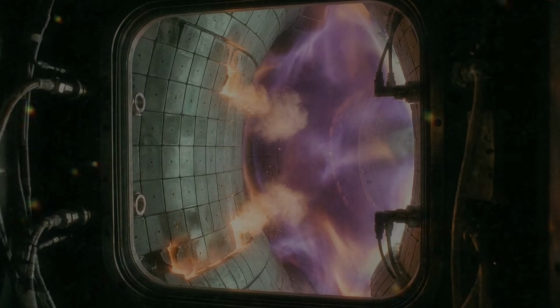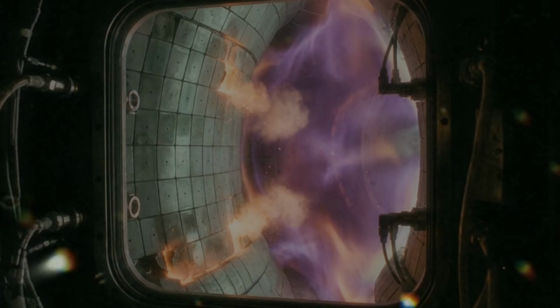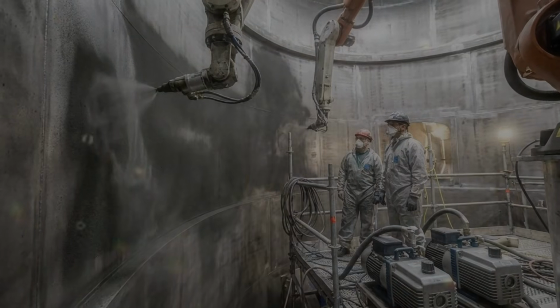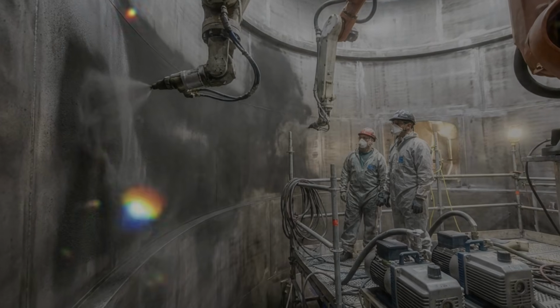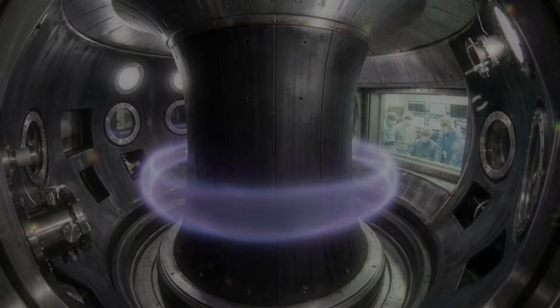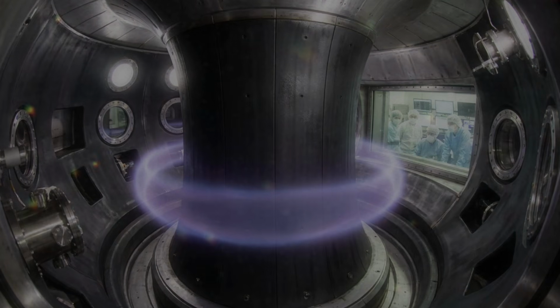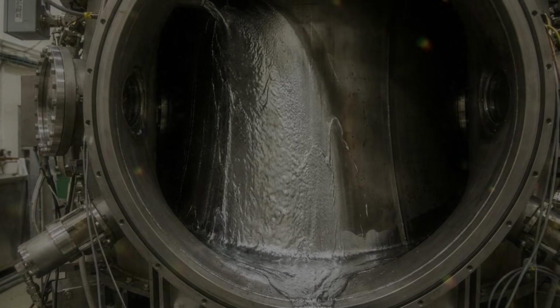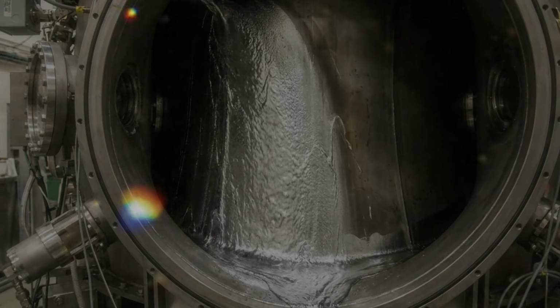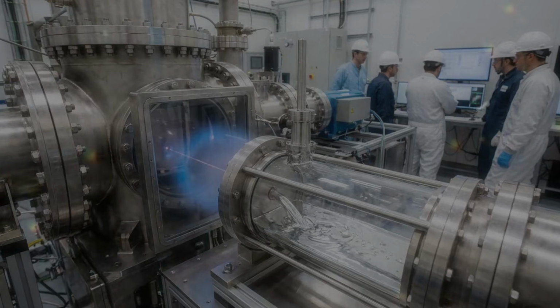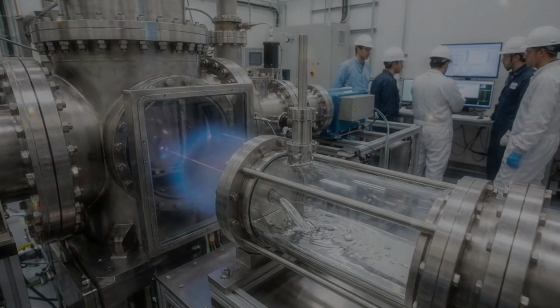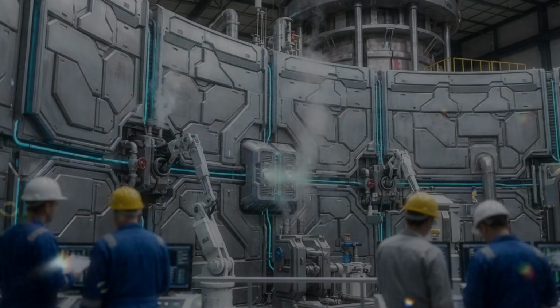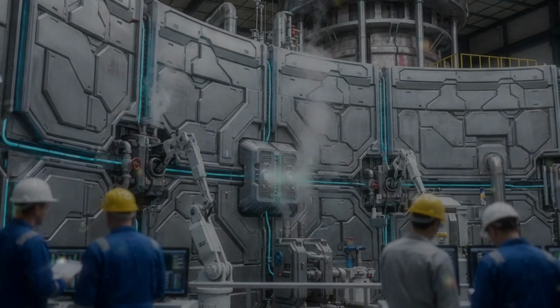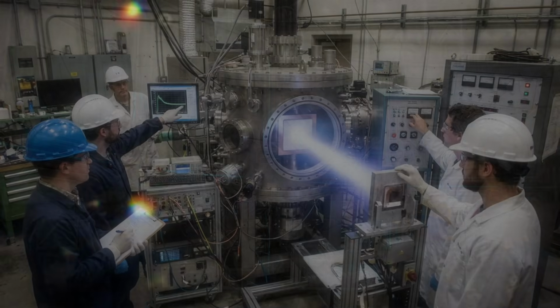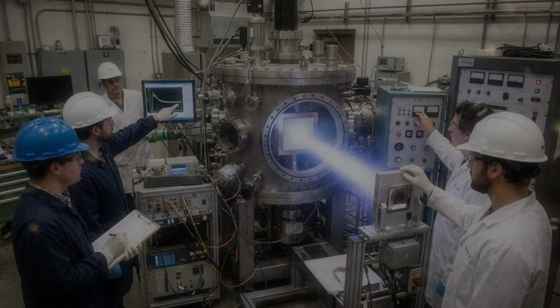Heat can also change the surface itself. If the temperature rises too much, atoms can move more easily. The material can recrystallize, soften, or lose strength. If a surface melts, even briefly, the problem becomes more serious. Liquid metal can move, splash, roughen, or resolidify in damaged shapes. A wall that was carefully manufactured with smooth surfaces and controlled geometry can become uneven. Uneven surfaces can interact badly with plasma, creating new places where heat concentrates or material erodes. Damage changes the wall, and the changed wall can invite more damage. It is a very unhelpful friendship.